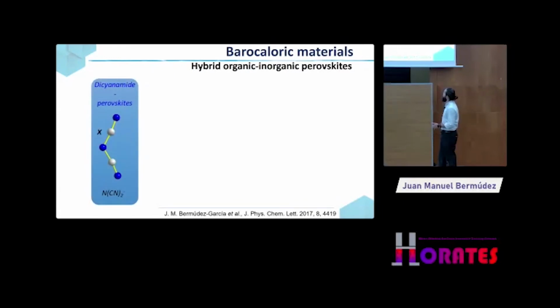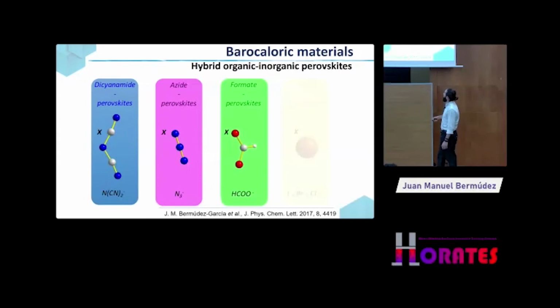So we decided to explore the literature, trying to find new materials that can fulfill not only the entropy change and the pressure requirement, but also the temperature span. We decided to explore other hybrid perovskites, but instead of using dicyanamide ligands, we were searching for materials with different ligands: azides, formates, and even halide perovskites, where you keep the organic parts in the middle of the pseudo-cuboctahedral cavities.